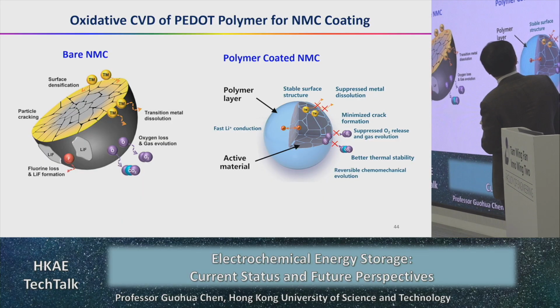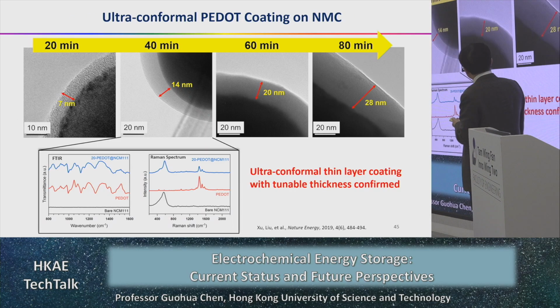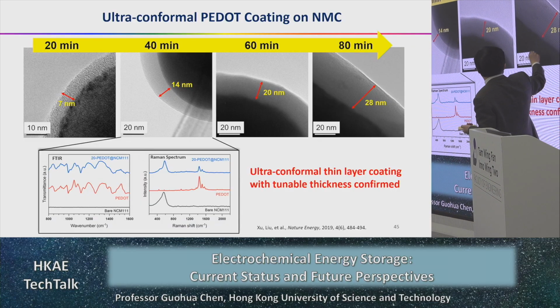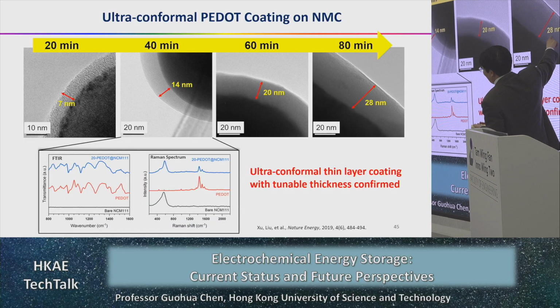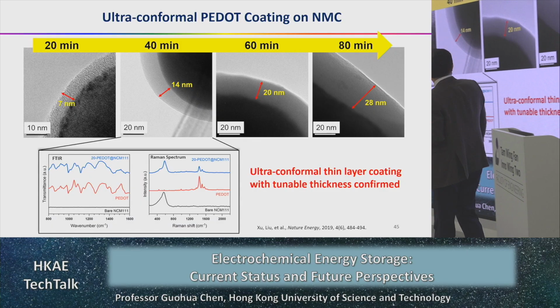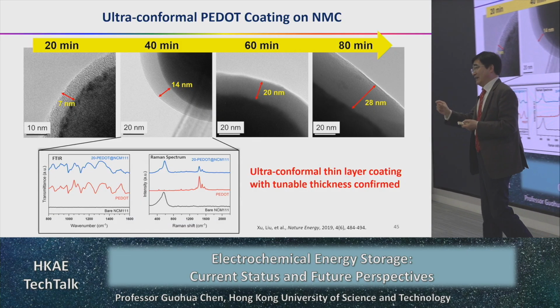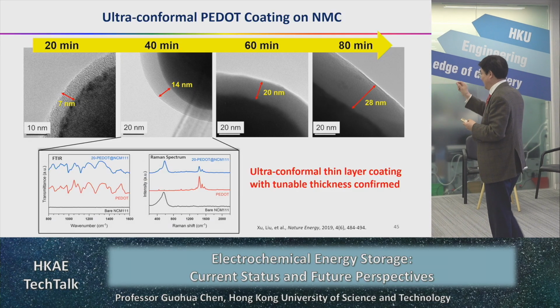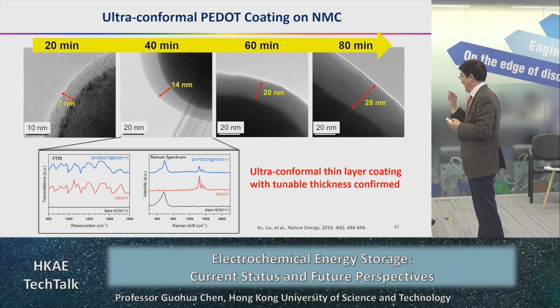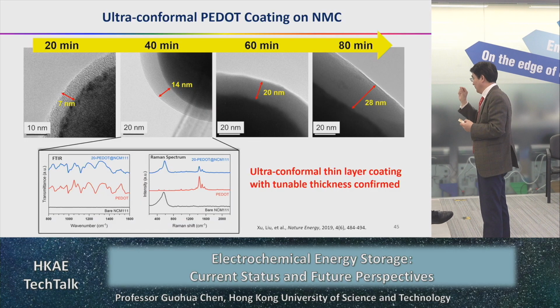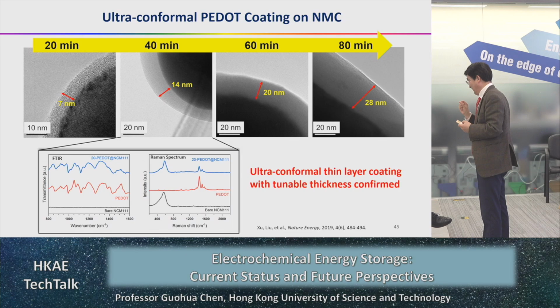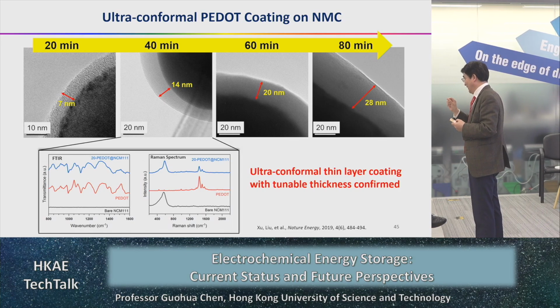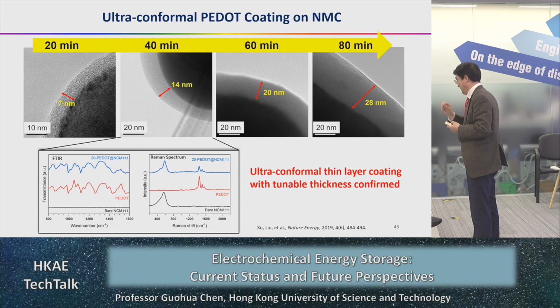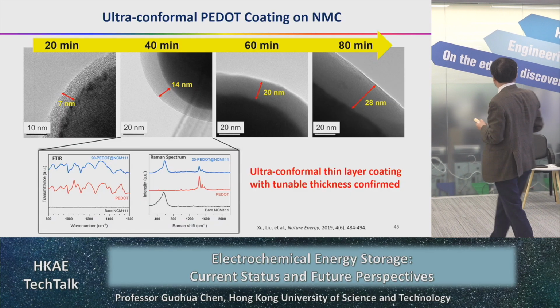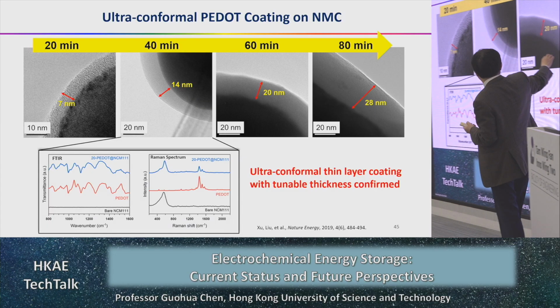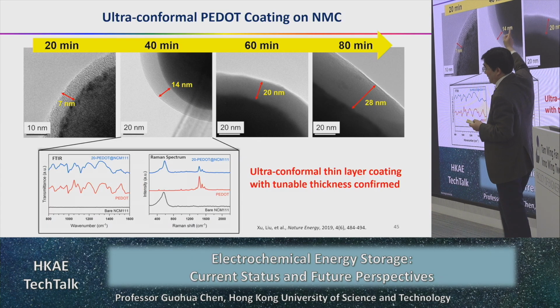And next one is coating. We coat very thin, maximum we're talking about 20 nanometer. What kind of dimension is 20 nanometer? Our hair is 50 to 80 micrometer, that is 50 to 80,000 nanometer. That's our hair diameter. So this is a really, very thin layer of polymer, conductive polymer PEDOT coating.